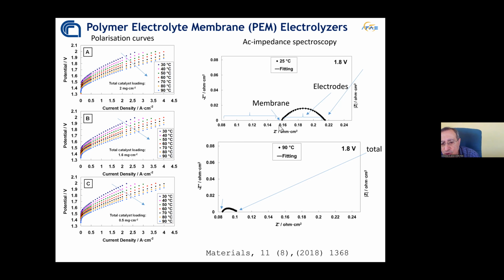We can understand the contribution of the membrane, the contribution of the electrodes, and how much is the total resistance. In order to achieve higher performance, we need to decrease this total resistance. How? As an example, by increasing temperature or by increasing catalyst loading. So electrochemical diagnostics allow us to understand which aspect we need to improve to achieve better efficiency.